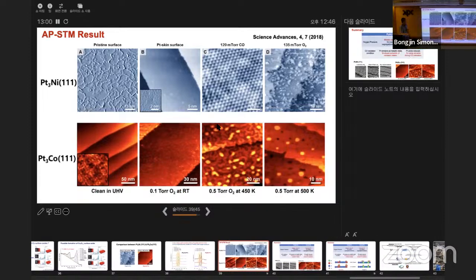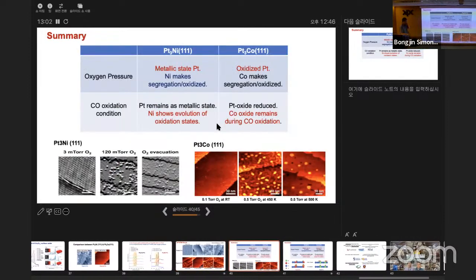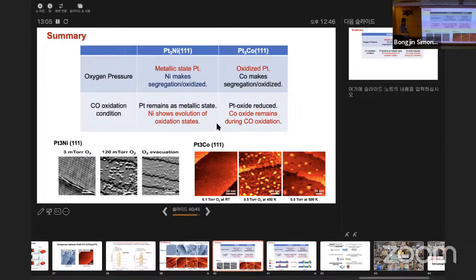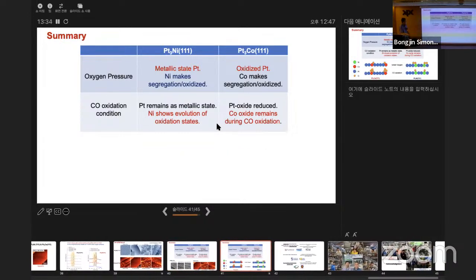So with that, I would like to summarize what I have. So platinum-3 nickel, platinum-3 cobalt, we clearly see this different chemical state of the platinum. And under the CO oxidation reaction studies, nickel shows a very dynamic state that changes dramatically, but the cobalt still remains on the surface, and the reaction is not as distinct as in platinum-3 nickel.